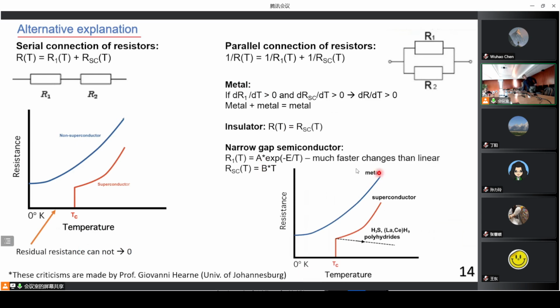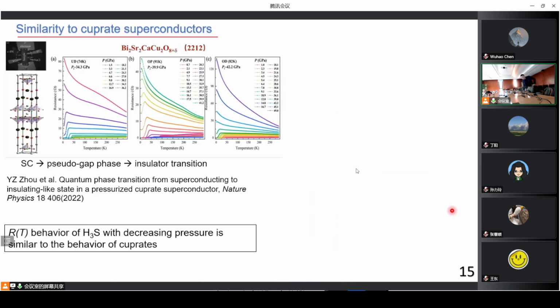So for metals, we should see such a plot, which can be described within the Bloch-Grüneisen formula. For a superconductor, before the transition, for a classical conventional BCS superconductor, we should also see metal-like behavior. But in hydrides, at least in H3S and lanthanum-cerium H9, we see behavior which is completely different and very strange. So some strange physics that was also recently observed in the cuprates.